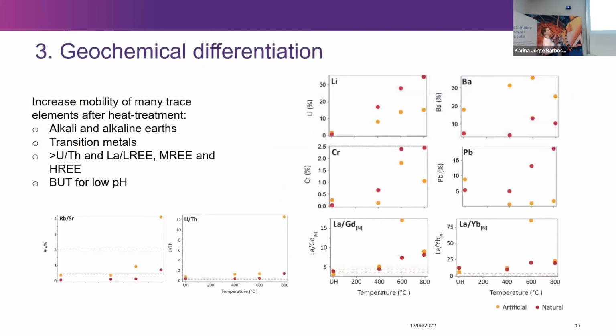So lastly, the last big takeaway was the geochemical differentiation that I found in these fire-affected samples. I took some samples, I heated them to different temperatures, and then I used weak acid extraction to look at what elements might be mobile following heating. And what I found was that heating actually increased the mobility of a lot of different elements. This is really obvious in things like the alkali and the alkaline earth elements, and in a lot of transition metals. So vanadium, scandium, chromium, cobalt, zinc, copper all had increased mobility following heating.